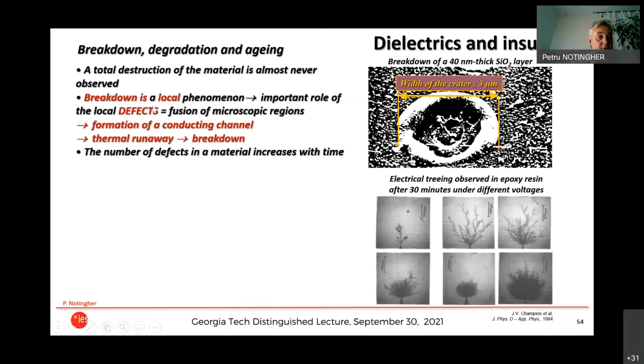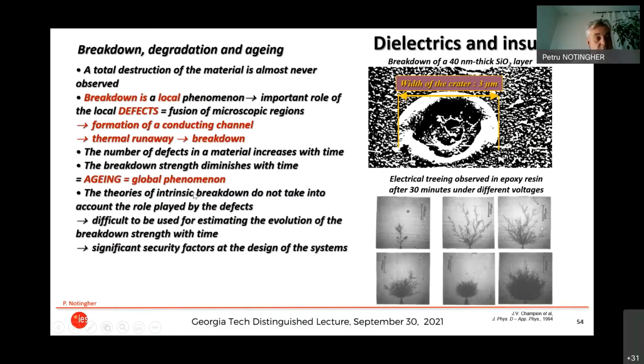So the most important role in breakdown is the role of local defects, which will lead to the formation of conducting channels, which will then be the subject of thermal runaway and will give breakdown. And as the number of defects in the material increases with time, the breakdown strength diminishes also with time. So this is the phenomenon of aging. But the aging is a global phenomenon. It's not a local one. So the material will age globally, but it will result in some weak points in a local breakdown.